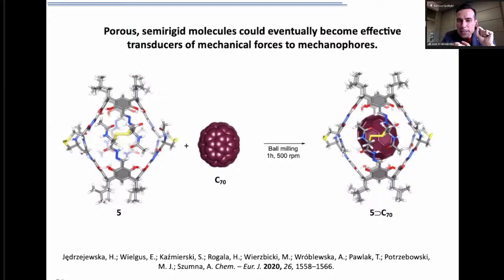The thing is that the pore that the capsule has is not that big. It's not big enough for C70 to go inside. So how did the process occur? The thing is that during the collisions, the capsule transduces the mechanical force to the sides of the porous molecule. And there you have some places where those functionalities could be broken apart by mechanical force, and they could reassemble later after the reaction proceeded. So the encapsulation occurred because ball milling was promoting the cleavage of, let me show you here, the cleavage of those bonds which were forming the capsule.